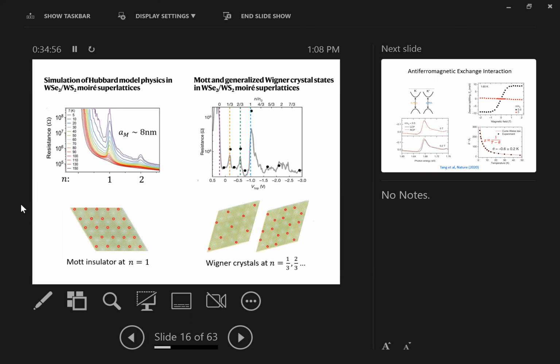Okay. Now things can be more interesting because in these systems, the number of doped charges is controlled by electrostatic gating. So it can be continuously varying from 0 to 1 to 2, or it can be anywhere in between. So at 1/3 and 2/3 filling, right? So we can have a situation where the number of electrons is a fraction of the number of these artificial atoms. So in this case, you get an interesting situation that again, because of the strong Coulomb repulsions, you can get formation of Wigner crystal states. Electrons can spontaneously crystallize into a periodic superstructure.